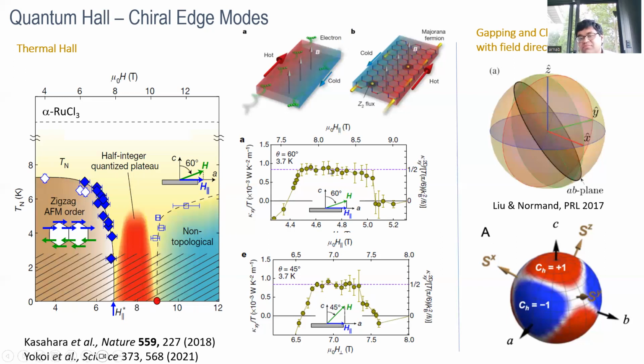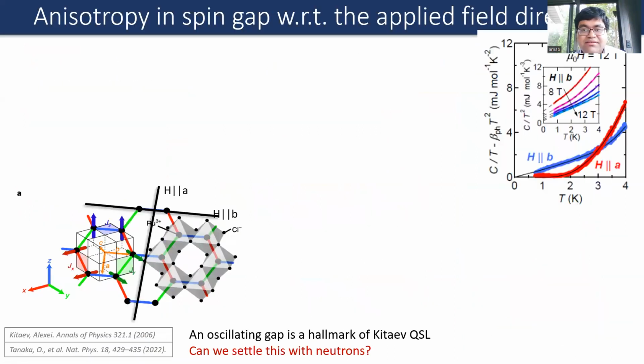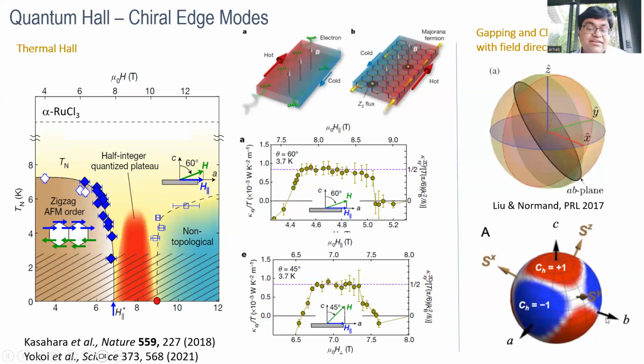You can see the edge modes here, and those are the half quantized edge modes, and that is more of a smoking gun signature that you do have Majorana fermions there, which are half quantized. One of the predictions is that you don't see the Majorana fermions for all directions of your magnetic field. You only see them along certain directions, which is nicely laid out in the Liu and Normand PRL paper in 2017. And indeed they did not see any quantization when they applied the field along the B-axis, but they did see a quantization when they applied the field along the A-axis.